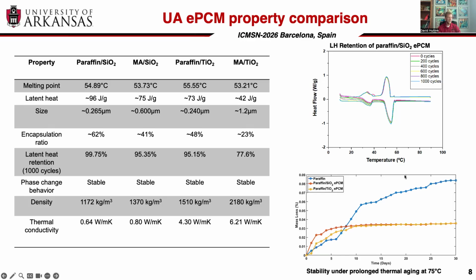And we also see that as we look at the stability of the actual PCMs over time, if we were just to sustain high temperature of paraffin, for instance, over a long period of time, we see a lot of evaporation of that paraffin itself and deterioration, and that would continue indefinitely. However, in the case of the encapsulated versions, we see that there is very minimal mass change in the initial stages, and then it's very stable from there on. So the shell is effectively holding all that together and keeping it from leaving the system.